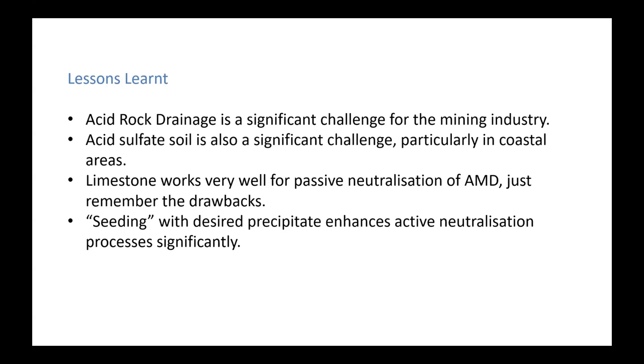Limestone works very well for passive neutralisation of acid mine drainage, but there are some challenges we saw with the coating precipitates that occur, but also some pretty pragmatic solutions using dozers to break off that crusting. John mentioned seeding many times. So seeding was something that I wasn't familiar with when I first read the slides, but it is seeding with some of the precipitates that you're looking to get. That was found to significantly improve neutralisation processes.